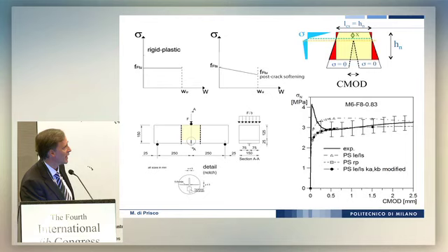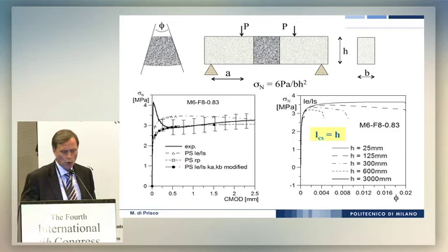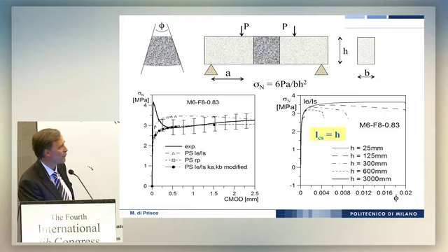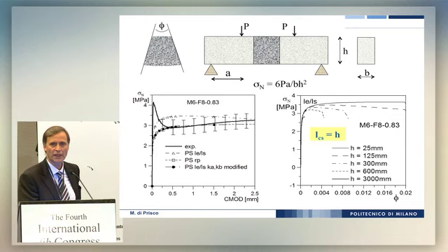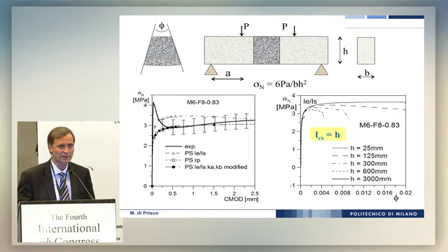It's obvious that sometimes we can use this model in order to reduce as much as possible the difference between the prediction and the real behavior, but it's also obvious that if you have a sort of elastoplastic behavior after the cracking, sometimes even the rigid plastic model can give you the best. And it's also important to highlight that if I consider the characteristic structural length equal to the depth, and you have, for instance, such a kind of beam with only fibre-reinforced concrete without any reinforcement, if you increase the depth, you progressively reduce the ductility, and so you pass from a ductile behavior to a very brittle behavior. That means that you cannot use only fibre-reinforced concrete for a deep beam. And so we don't need any other parameter, because with the structural characteristic length, you have also the possibility to capture this very important size effect.